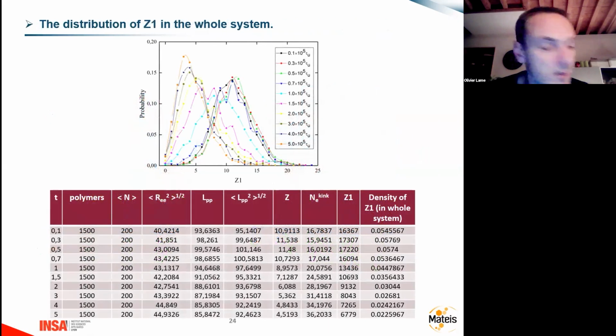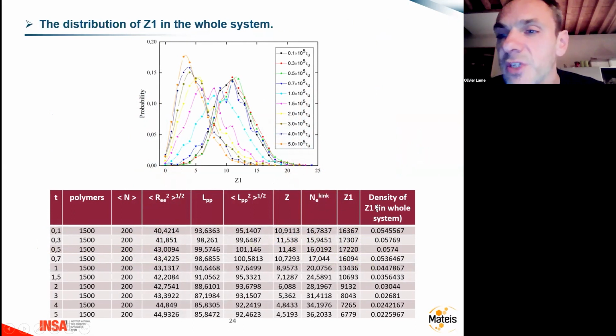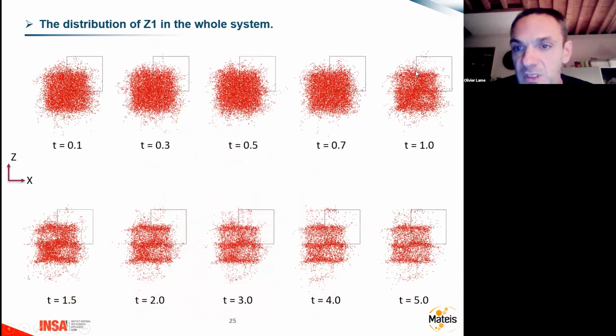Okay, so we use this algorithm with our system, and then we found, in fact, a decrease of the density of Z1 here, which are the entanglements, with the crystallization. Okay, and this is for the whole system. So it means that the crystallites are also destroyed by this algorithm, and then the localization of these entanglements is nearly everywhere.